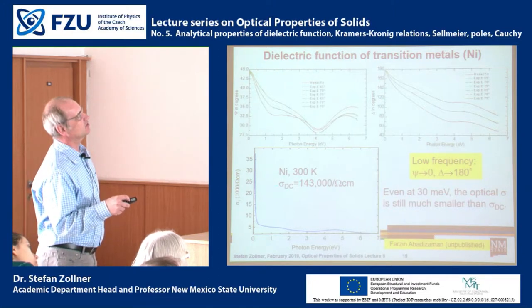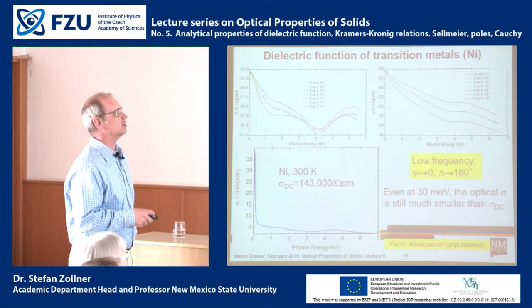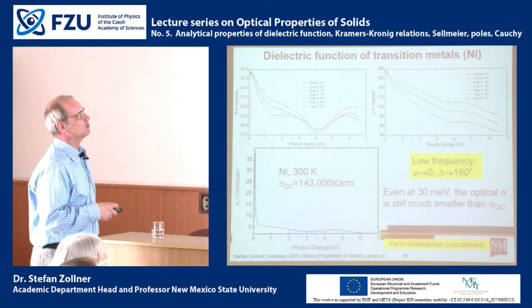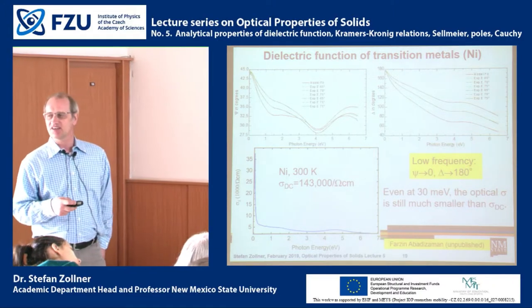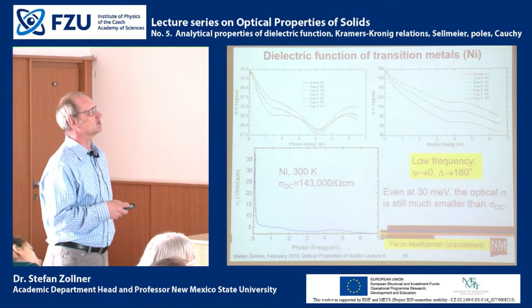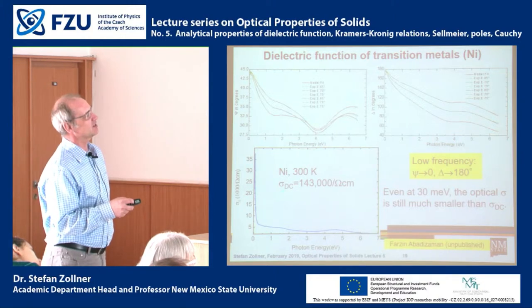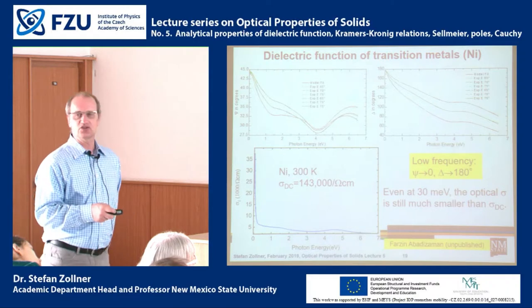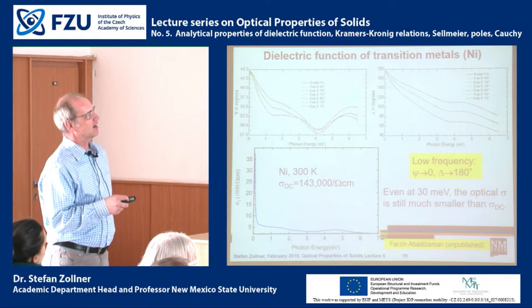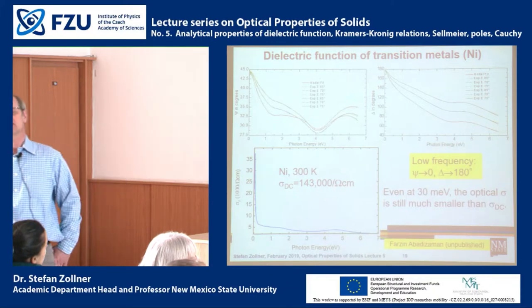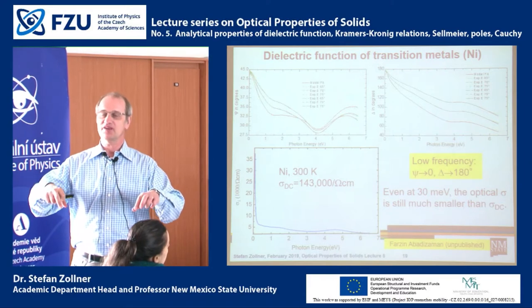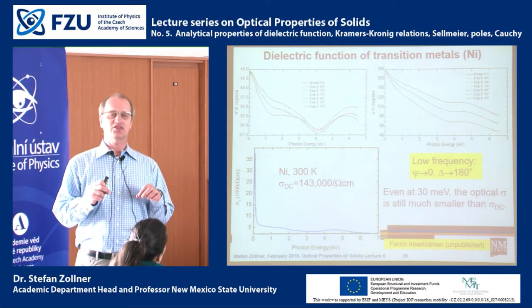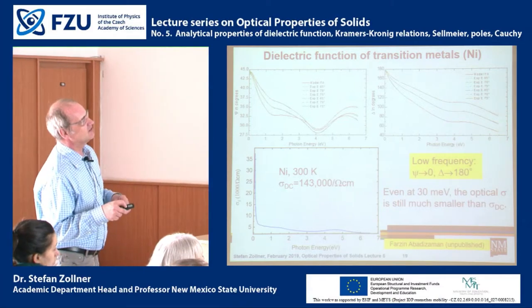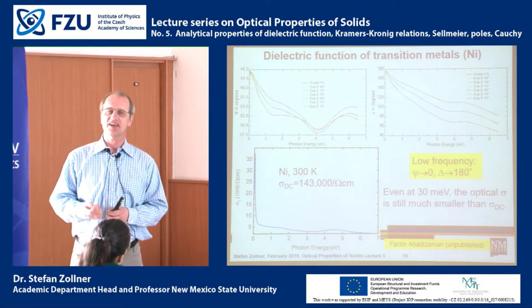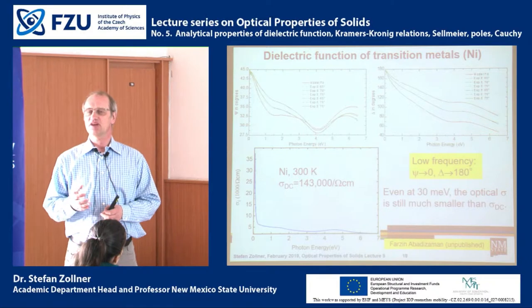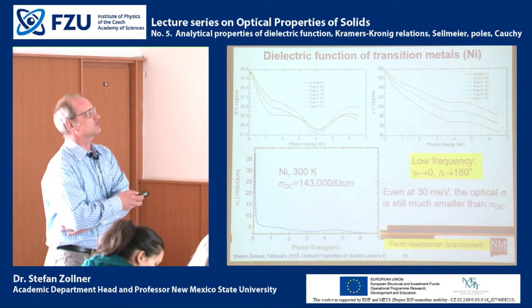The DC conductivity of nickel is 143,000 per ohm centimeter. That's a number taken from the literature. So one of my goals has always been, can we measure the optical conductivity at long enough wavelengths so that we can actually recover this DC conductivity using optical methods? So why do I want to do this? Well, how do you measure this DC conductivity? You take a piece of nickel and you need to apply 4 contacts, and then you do an electrical measurement. So if one could measure the DC conductivity using optical techniques, then one would not have to apply contacts, and that would be a much faster and non-destructive way of measuring conductivity.